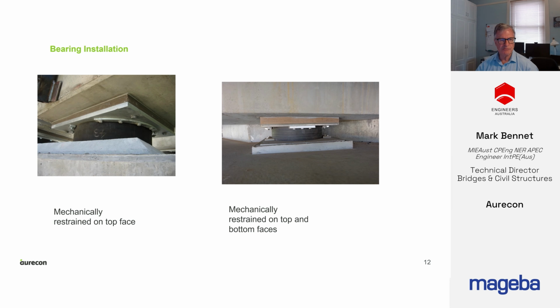So this is a photo of a standard bearing installation that's done in New South Wales. The tapered pre-moulded epoxy mortar pad with the steel plate that's screwed and bolted and glued to the soffit of the girder. There's keeper plates that are bolted onto the top attachment plate. The bottom mortar pad should be detailed to extend at least 50 millimeters past the face of the bearing, so that a minimum of 25 millimeters will be achieved, accounting for construction tolerance.